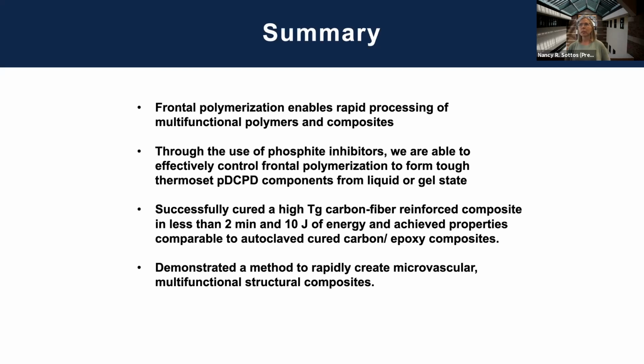So I have a summary slide there that, basically, frontal polymerization enables rapid processing of composites. Through the use of these inhibitors, we can form fairly complex components and parts, either from liquid or gel state. We've gotten high Tg carbon fiber composites in relatively short times with low energy. And we've demonstrated a method to make multifunctional structures like this.